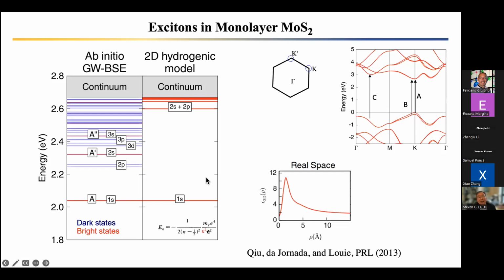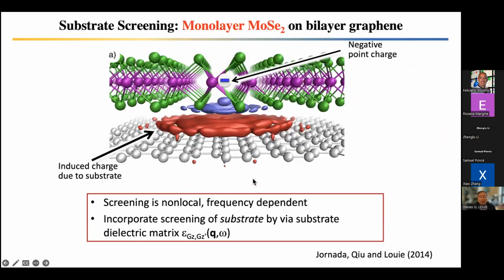So that means that the higher excited states with larger excitonic wave function will be weakly screened. Therefore, they would have bigger binding energy. And in fact, the 2p states would have a bigger radius than the 2s states, and therefore this explains the angular momentum dependence of the binding energies.